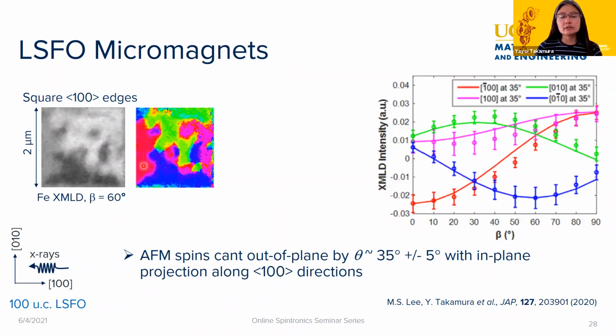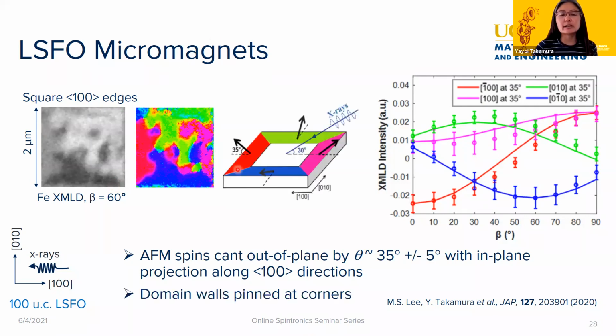And what you'll notice is that the red one is always on the left, the green one is at the top edge, the pink one on the right edge, and then the blue one at the bottom edge, right? And what you see is that the domain walls between them get pinned right at the corners. And so the schematic that we came up with is that we have these domains canting out of plane, and then the domain walls want to pin at the edges. And so we get this edge preferred orientation of the antiferromagnetic spins. And in the center, you basically get just random domains, which don't really care about what's going on at the edges. But over about a 300 or 400 nanometer range, we can get this region where we can use the shape of the nanomagnet to dictate what the local antiferromagnetic spin structure is.